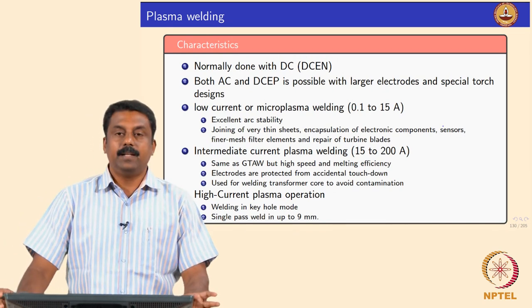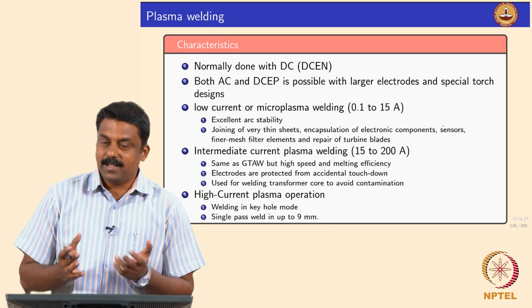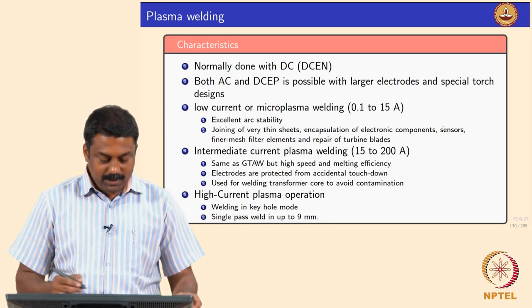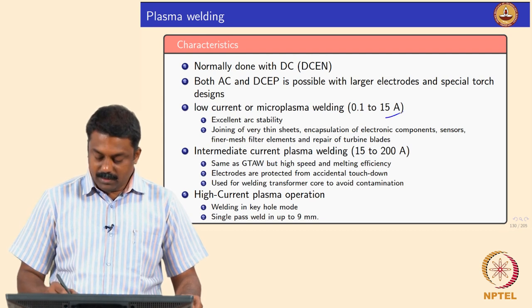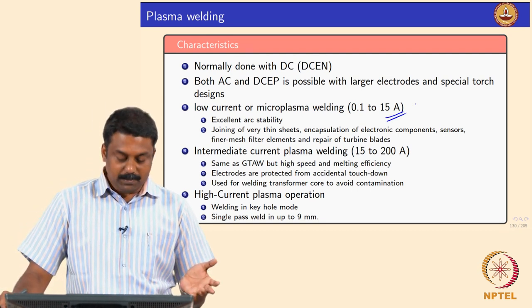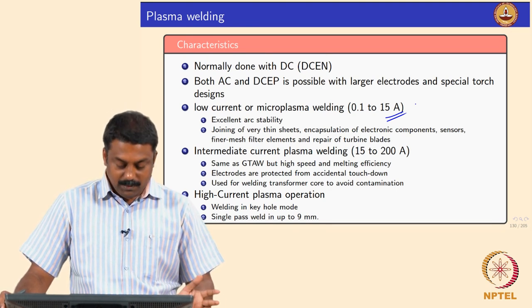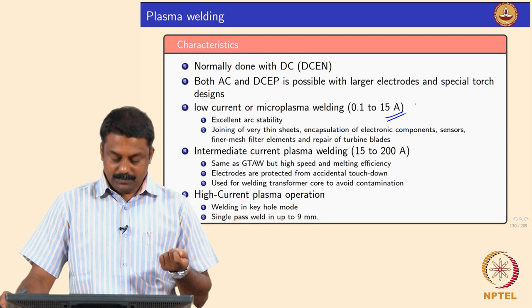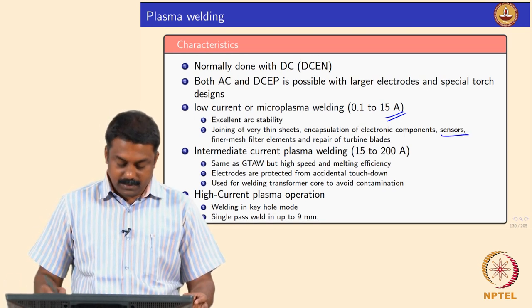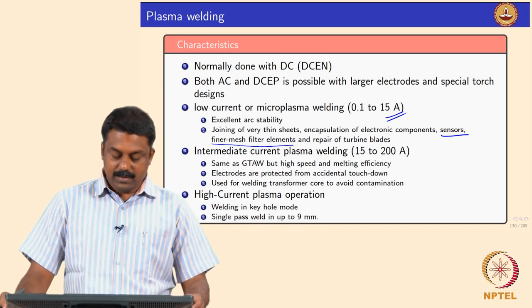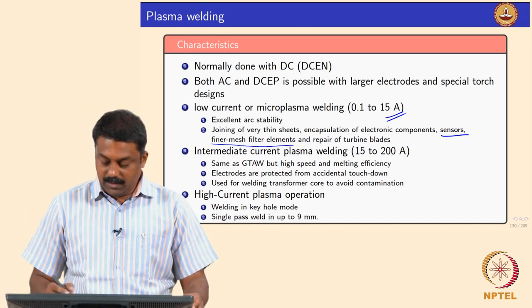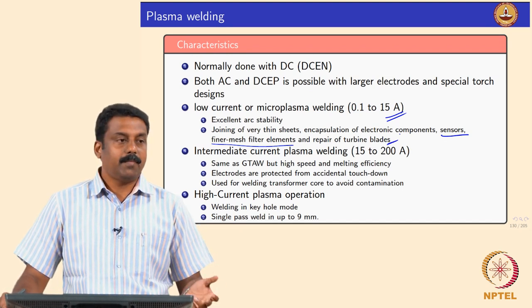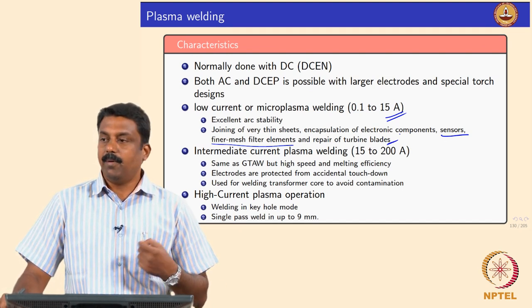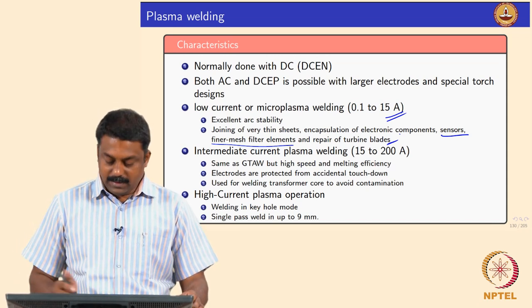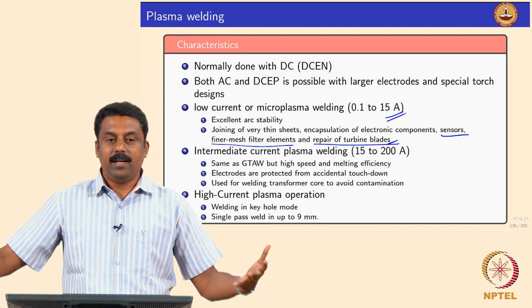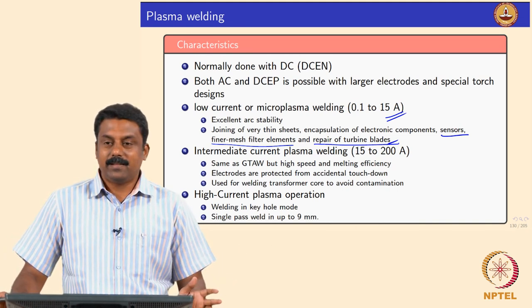Some of the characteristics I mentioned: we can generate plasma with even very low current. We can do it at various amperages, with an extremely low amperage of 15 amps. That's called microplasma. We can still get very good arc stability. It is used for welding very thin sheets, electronic components, for example sensors, finer-mesh filter elements, and sometimes we also use microplasma to repair already worn out parts by depositing with powder or with the wire.